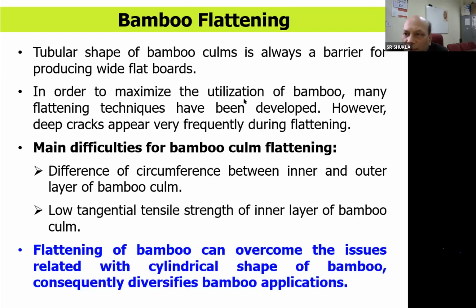So in order to maximize the utilization of bamboo, many flattening techniques have been developed. However, deep cracks appear very frequently during flattening. So these cracks need to be avoided. These are the main difficulties for bamboo flattening: the difference of circumference between the inner and outer layer of the bamboo, because the outer layer will have a larger diameter compared to the inner one, and the lower tensile strength of the inner layer of the bamboo compared to the outer layer.